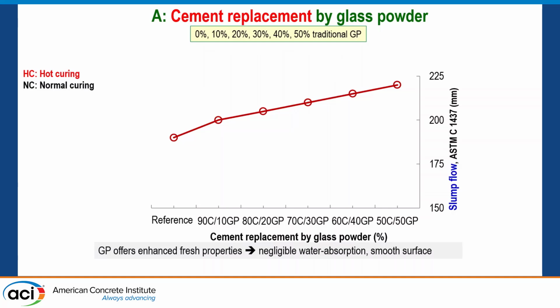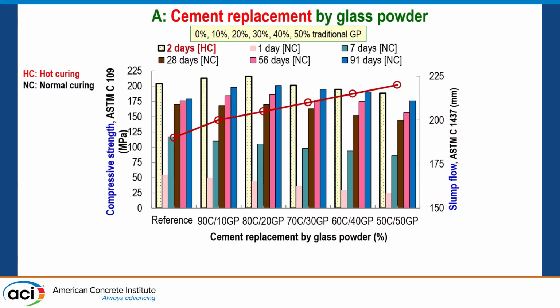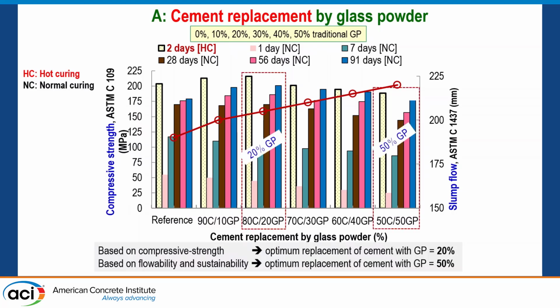So when we work here, this is the slump. You can see that as we add more glass, the slump is increasing from 0 to 50%, then the compressive strength also is increasing when the slump is low, but if you put very high slump, then you decrease a little bit your compressive strength when you replace a lot. So the optimums we found here: if you want high compressive strength, you can go to 20% glass powder. If you want more flowable, then you can go up to 50% of glass powder.